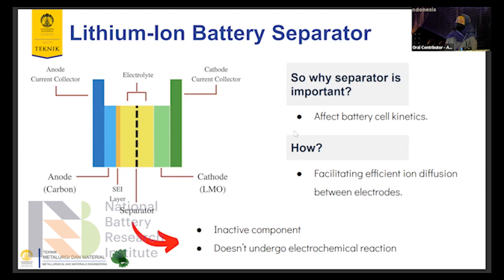Why do we talk about lithium-ion battery? Because lithium-ion battery is lightweight. Also, it has a high energy and power density. Basically, lithium-ion battery has four main components, which are anode, cathode, electrolyte, and separator. Separator doesn't undergo any electrochemical reaction, so it is considered to be an inactive component. However, it can affect the battery performance because it affects the battery cell kinetics. Why? Because in the separator, there will be lithium-ion transport between those electrodes. So the sufficient and efficient ion diffusion between the two electrodes will affect the battery performance.